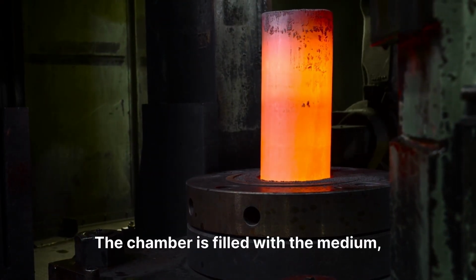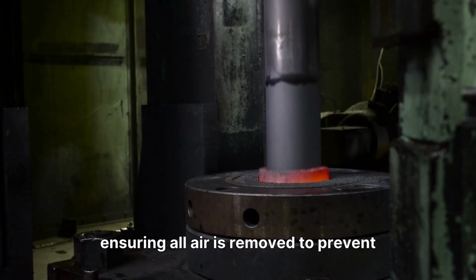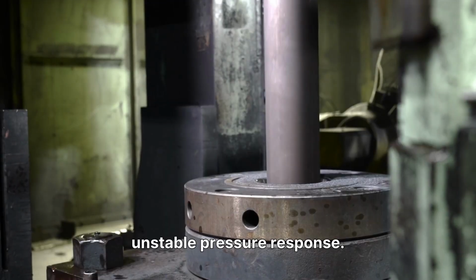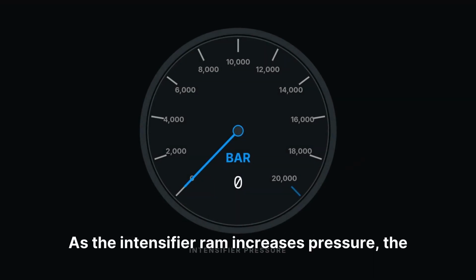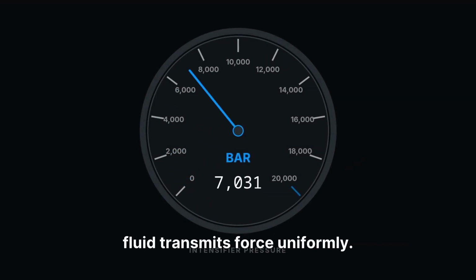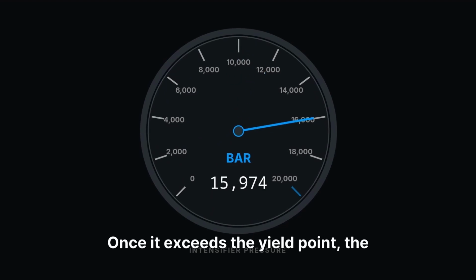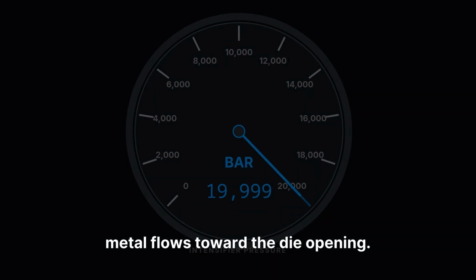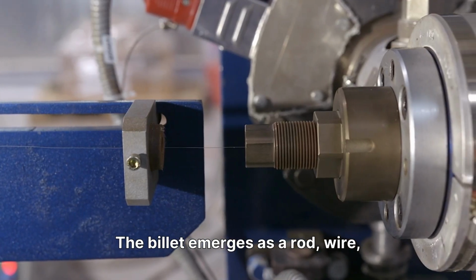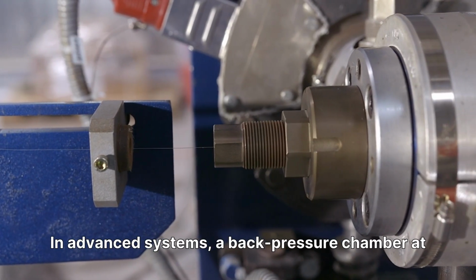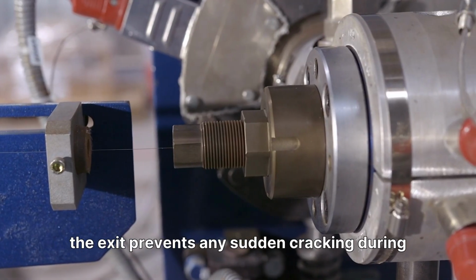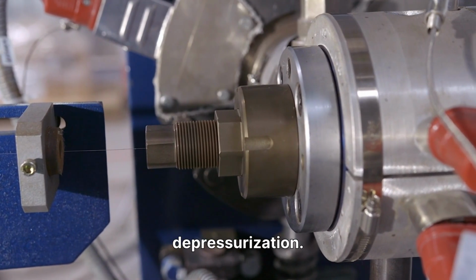The chamber is filled with the medium, ensuring all air is removed to prevent unstable pressure response. As the intensifier ram increases pressure, the fluid transmits force uniformly. Once it exceeds the yield point, the metal flows toward the die opening. The billet emerges as a rod, wire, or tube. In advanced systems, a back pressure chamber at the exit prevents any sudden cracking during depressurization.